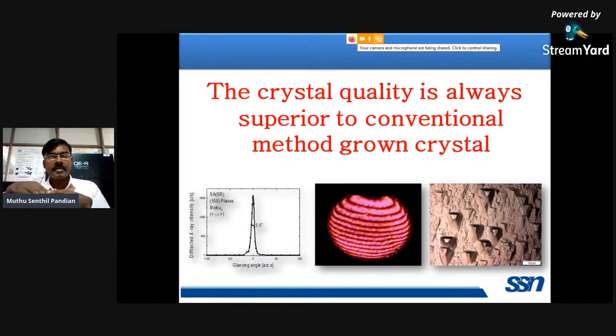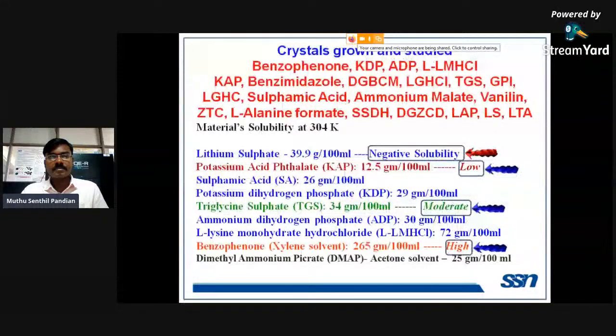Almost, we have confirmed we have grown the crystal under identical conditions with two different methods, that is the conventional method and this SR method. Under identical conditions, we have seen the structural properties, the physical properties, and the crystalline perfection. We have confirmed, and the final conclusion is that the crystal grown by the SR method is always superior compared to the conventional slow evaporation method grown crystal.